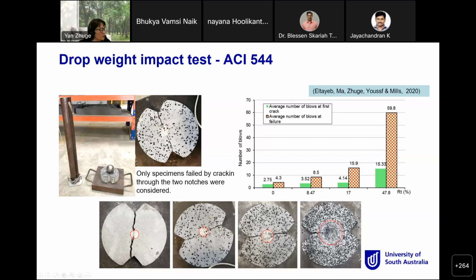You can see the normal concrete and the crumb rubber concrete with different percentages. You can see the improvement in the failure pattern of these samples when you use more crumb rubber. And this one shows the number of blows. You can see the average number of blows at failure. Where you have a large amount of crumb rubber, there is a significant increase in the number of blows. So that is very good for the impact resistance of crumb rubber concrete.